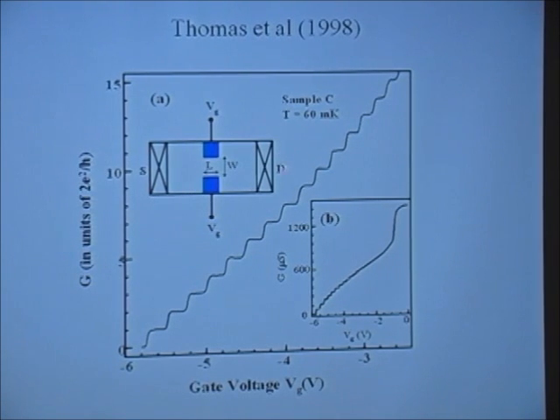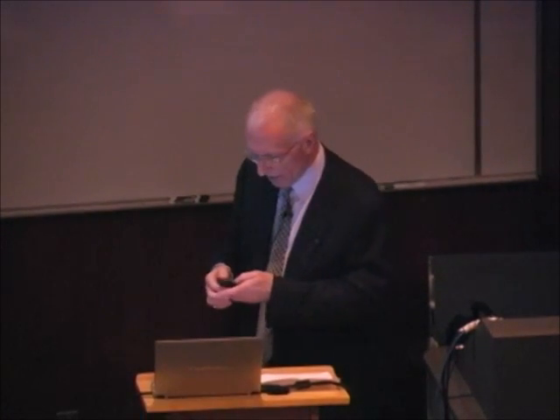So what one can see in an experiment is up to 30 quantized levels. And that means, if you think about it, think of the nodes of the wave function. We start off with half a sine, and then a sine, and then more and more nodes. We've got about 30 nodes, all of which are independent. There's no scattering in the channel, so there's nothing to mix these levels up at all. The electrons behave as if they're in resistors in parallel, completely independent of each other.